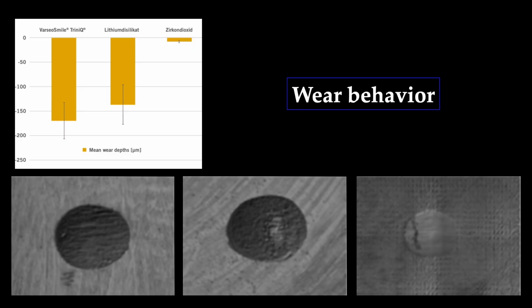What about wear behavior? Of course, the wear of our hybrid restoration is more than lithium disilicate, which is more than zirconia. So the wear resistance of zirconia is the best. Then comes lithium disilicate in the middle, and the highest wear will be in the hybrid ceramic. But what about the opposing? The opposing wear with zirconia is the highest. It gives us more than 20%. Lithium disilicate is in the middle. And the least wear on the opposing is with the hybrid ceramic restoration.